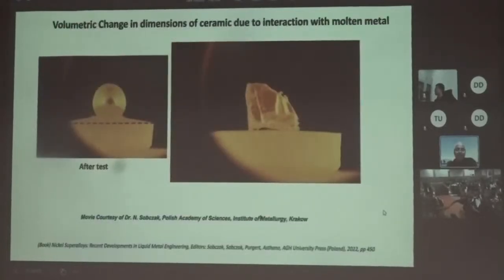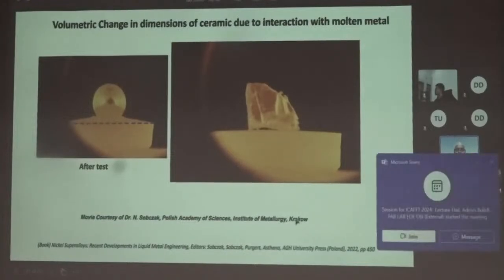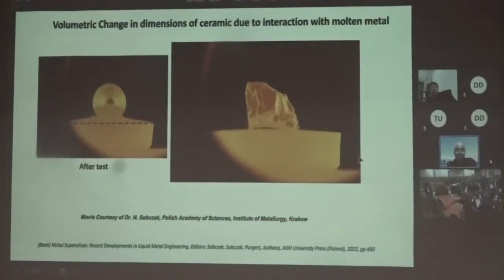Another thing we see is the real-time change in volume. Right now the surface is flat and horizontal, but with the reaction, it is changing. It is becoming more curvy because of the reaction and volumetric change. You can see the surface of the substrate becoming more curved, and that is what is going to cause the contact angle measurements to be in error.